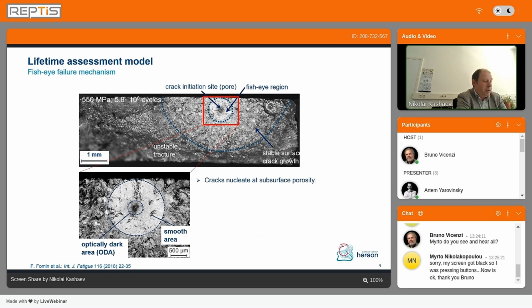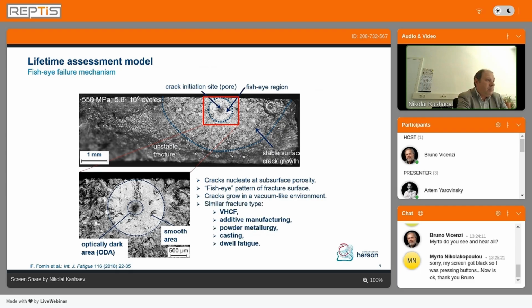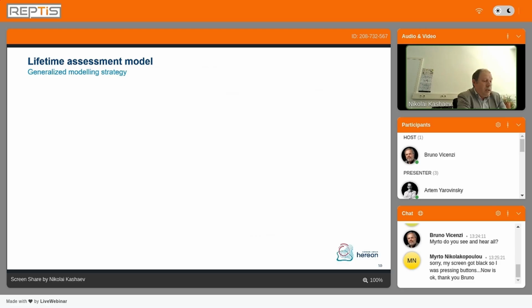Therefore, the most important remarks are that the cracks nucleate at subsurface porosity. We have a fish-eye pattern of the fracture surface, with crack growth in a vacuum-like environment, because if we have crack initiation from internal pores, we do not have the effect of the environment. And a similar fracture type is well known for very high cycle fatigue for every kind of additive manufacturing, powder metallurgy, casting, and dwell fatigue.